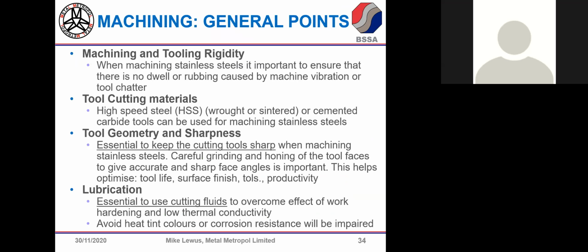So very quickly on machining, there's always the problem with particularly austenitic grades that they work harden readily. They're difficult things to machine, or certainly if you've got experience machining non-stainless steels, the work hardening means you've got to carefully look at machining parameters. It's also worth pointing out a rather obvious thing. It's not always considered, but you want to choose conditions that eliminate any machine vibration or risk of tool chatter.